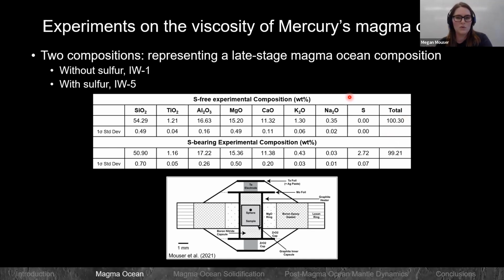You may also note that looking at these experimental compositions, there's no iron in here. That's because we tested an iron-free composition because of the very low iron content on Mercury's surface.